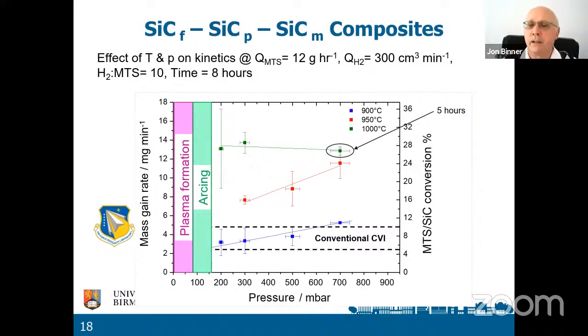Note that the data point that is circled has only had 5 hours rather than 8 hours. So after 8 hours of processing, we would expect it to be a little higher up that axis. That's an experiment we still need to do.